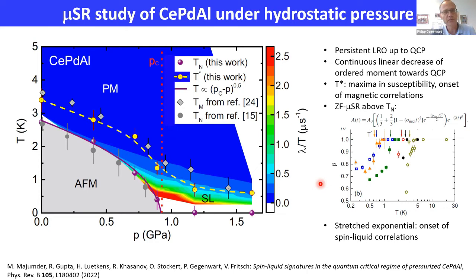And we did with Mayuk this study of muon spin relaxation under pressure. First he could confirm that the long-range ordered state disappears below 1.1 gigapascal, while the signature of magnetic frustration is present up to much higher pressures. The zero-field muon spin relaxation spectra were fitted by such a complicated form, where the exponent beta deviates from 1, the so-called stretched exponential behavior starts, and that's in general an indicator in geometrically frustrated magnets for the onset of spin liquid correlations.